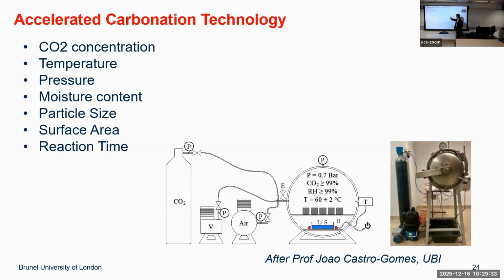So if the accelerated carbonation is affected by the carbon concentration, the reacting temperature and pressure, and also moisture content, sometimes you need a well-designed moisture component. I had a chance to speak with the professor, and he mentioned we need to do some modeling to find out the optimal moisture content and concentration, and use a semi-wet carbonation. Okay, and particle size and surface area.